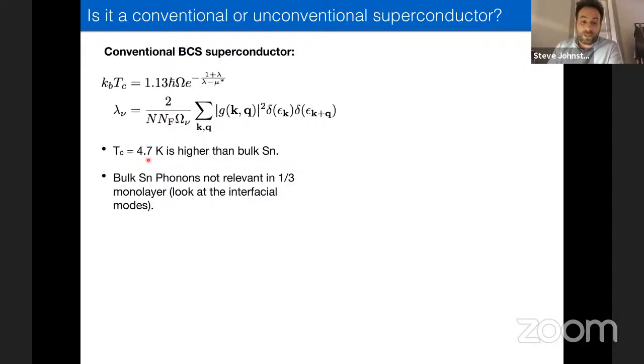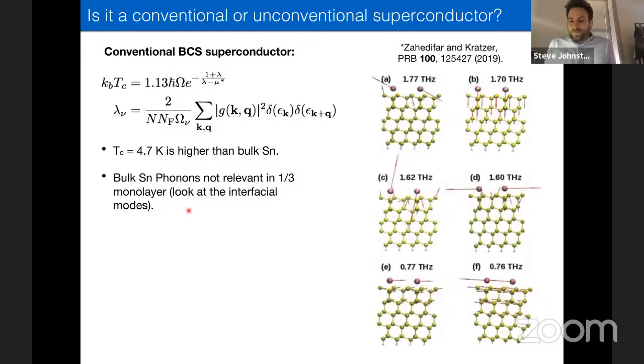The Tc that we get is about 4.7 Kelvin, and that's larger than what you would expect for bulk tin. Bulk tin, I think, is about 3.3, if I remember correctly, 3.5 maybe. So this is maybe not so surprising, simply because the monolayer has a very different structure. Remember, the atoms are separated by much larger distances than they would be in bulk tin. And so this indicated to us that what we really wanted to look at were not bulk phonons, but stuff associated with the monolayer. Fortunately, some people did the work for us.